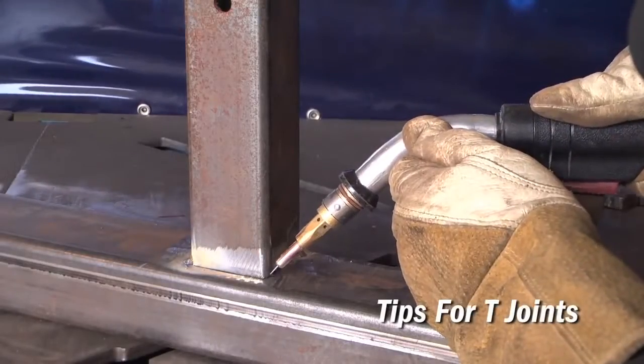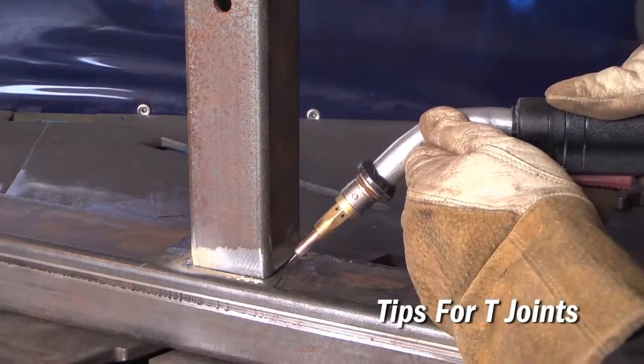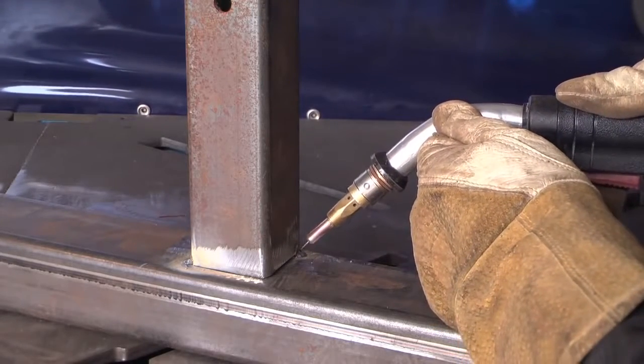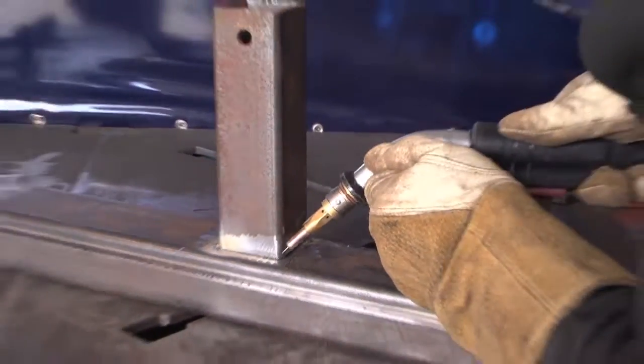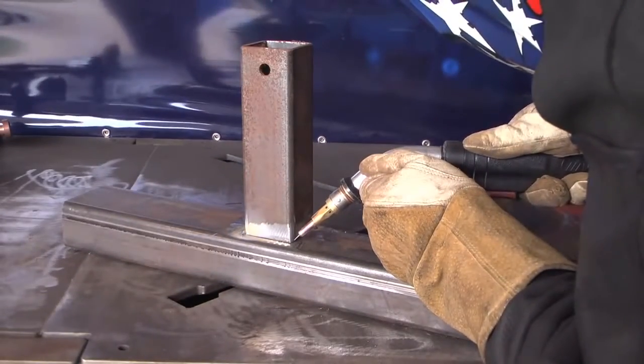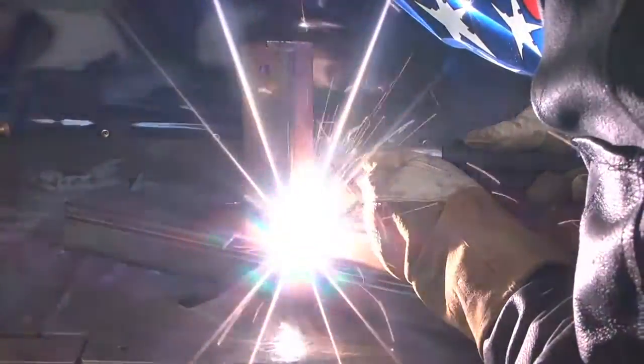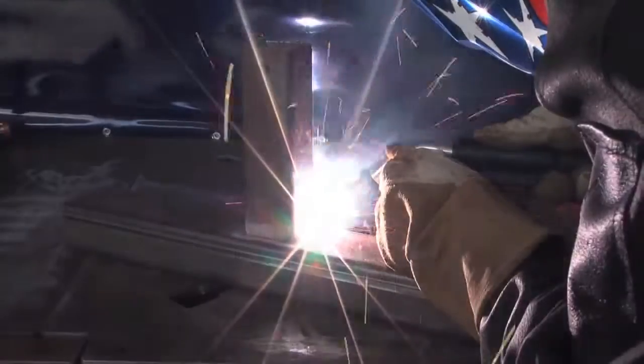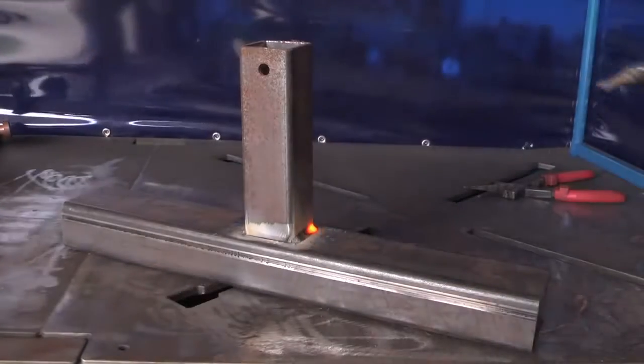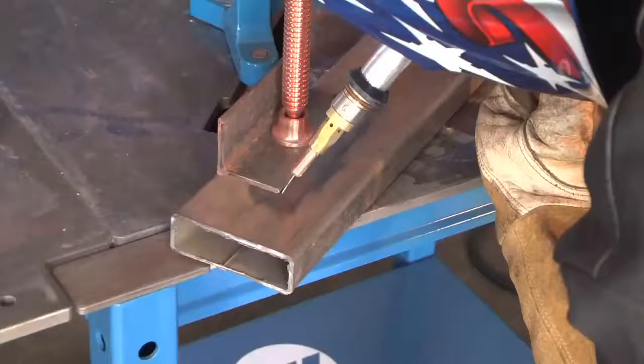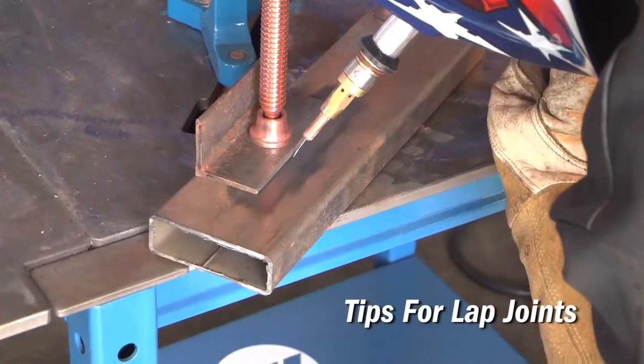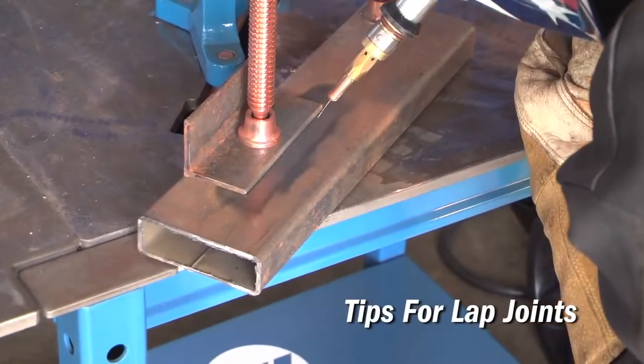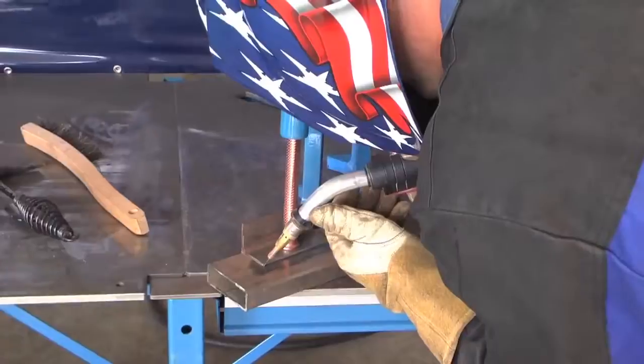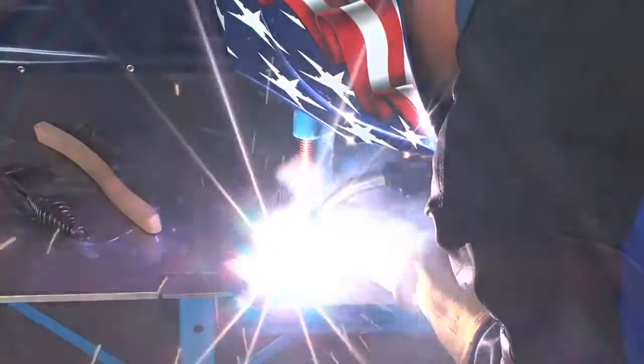For a typical T-joint, you're going to want the gun at 45 degrees or an equal distance from each piece. And on thicker pieces, you may want to weave the gun, pausing on each side to avoid undercut. For a lap joint, you're going to want your gun at 60 to 70 degrees, directing most of the heat toward the bottom of the workpiece. You make one straight weld.